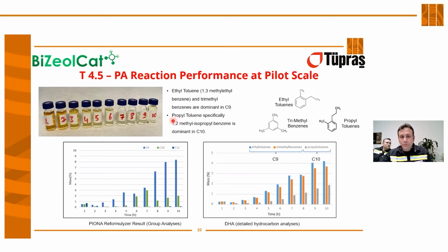Therefore, propane aromatization reaction is shown at pilot scale. We collected this liquid by chilling the outlet of the reactor at -10 degrees, because you cannot condensate this product at room temperature. You will get nothing in the collection vessel.